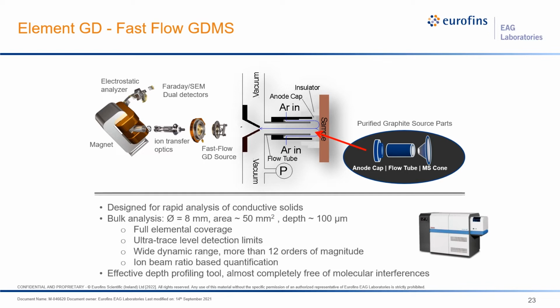An important characteristic lies in the purified graphite source parts that serve as the anode cap, flow tube, and mass extraction cone. The Element GD has several important features. It is designed for rapid analysis of conductive solids. For bulk analysis, its sampling size is 8 millimeters, with sampling depths in the hundreds of microns. Again, it has full elemental coverage, ultra trace level detection limits, and a very broad dynamic concentration range, actually more than 12 orders of magnitude. Again, it is based on ion beam ratio for quantification. One of the important features of Element GD is that it can do effective depth profiling, almost completely free of molecular interference.